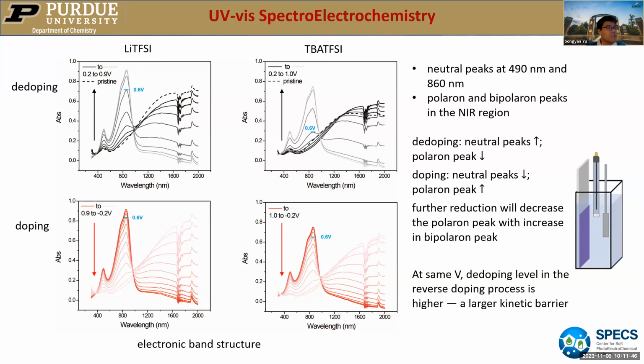First I start with UV spectroelectrochemistry. I just take two examples to show how they behave. First, we need to separate the de-doping process and the doping process. The polymer itself is self-doped, so what I did was de-dope it first and then dope it. What we can see first is that the de-doping and the doping are not actually symmetrical. I marked the absorption at 0.6 volt, and we can see there's a difference between these two. Also for TBA TFSI. Another striking difference is that at the same potential, lithium TFSI has a higher de-doping level, but TBA TFSI has a lower de-doping level.